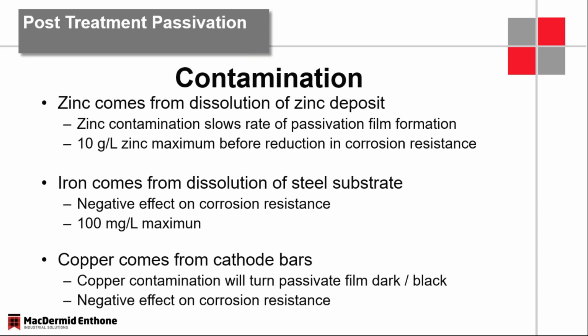Copper's a big no-no. Any copper in there and you have a dark film, no corrosion resistance. It's usually coming from copper bus bars or some other source of contamination. Copper is extremely poor for proper passivation.